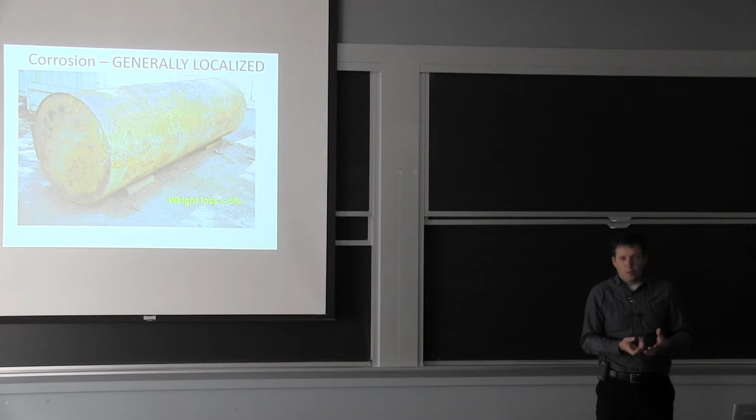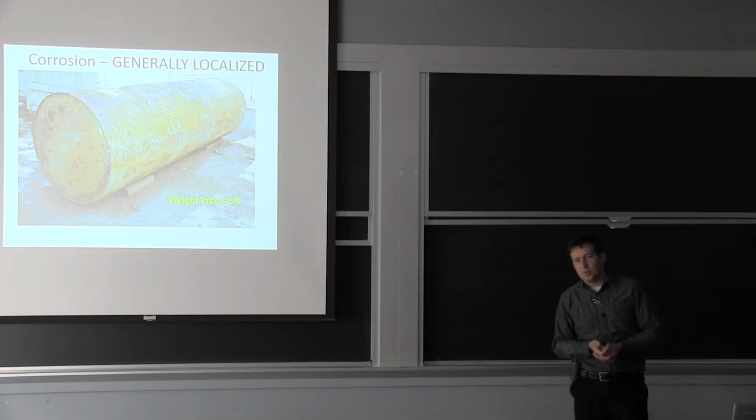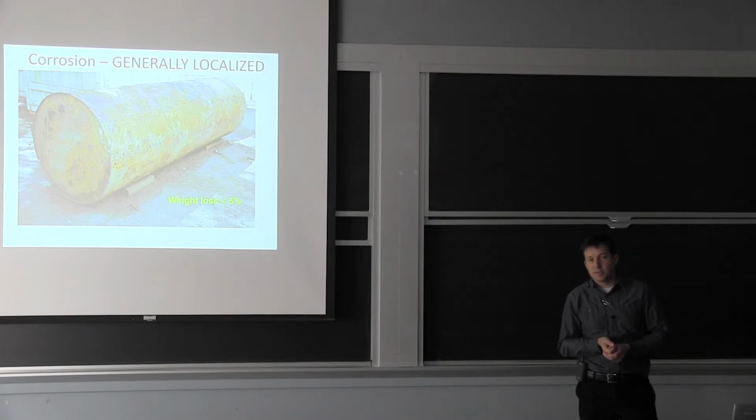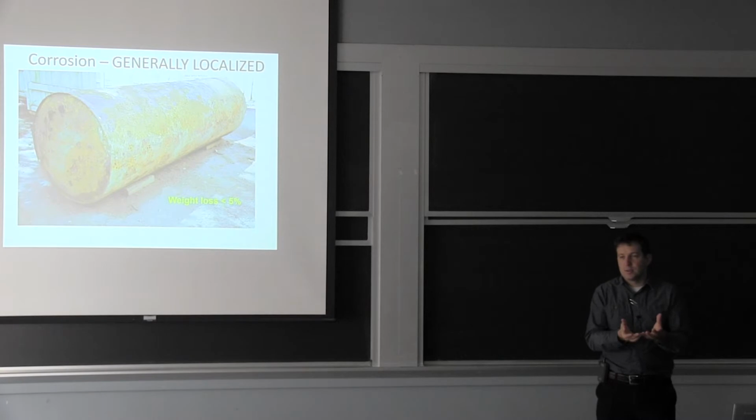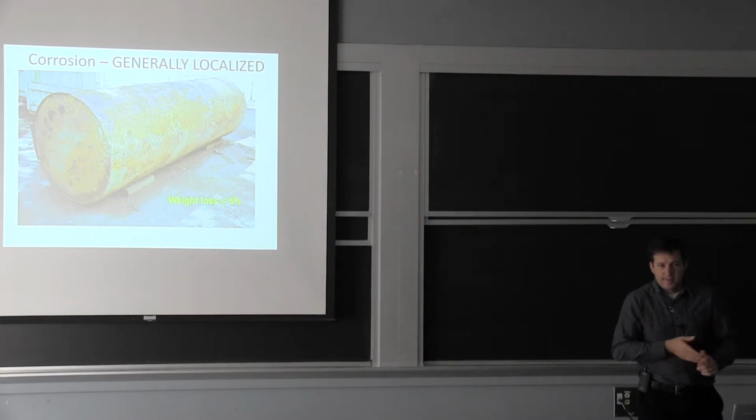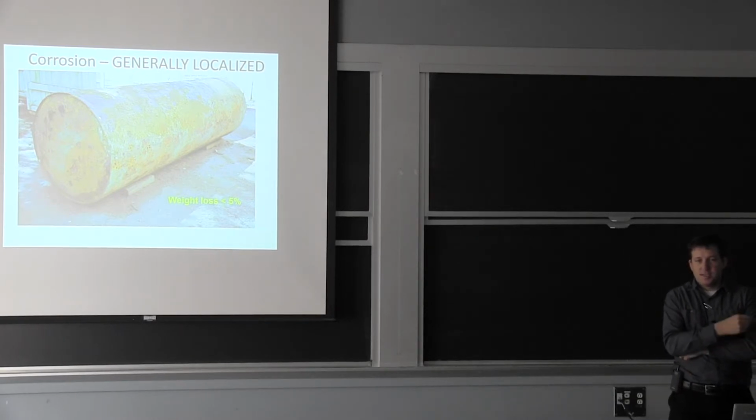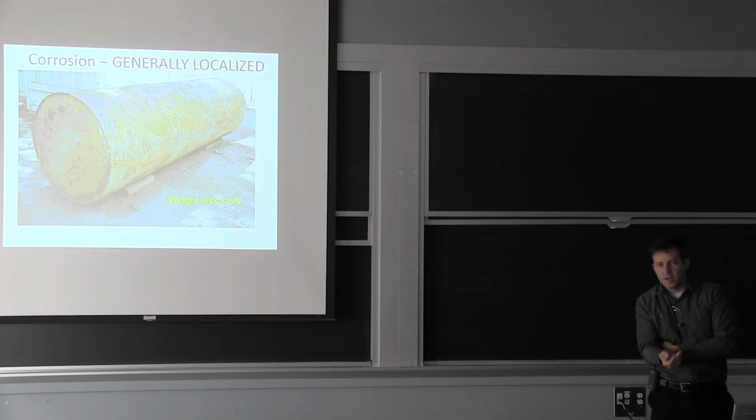From the time you perforate, it's not clear that that's when people realize they have a problem. And that's why we try to get as many of these out of the ground, because sometimes you can have a very small leak with the soil just essentially sealing the holes. So when we see the corrosion on the inside, some of it can just be moisture from the ground penetrating back into the tank and causing that corrosion. So there's just a lot going on.